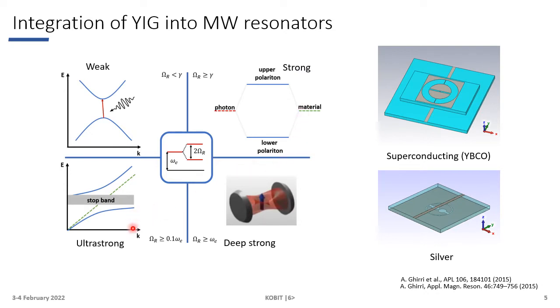When we start to compare the Rabi frequency with the base excitation frequency instead of the decay rates of the excitations, we are reaching the ultra strong coupling regime, and the condition for obtaining the ultra strong coupling regime is that the Rabi frequency should be at least 10% of the excitation frequency. And when we increase the Rabi frequency over the excitation frequency, we are reaching the deep strong coupling regime.